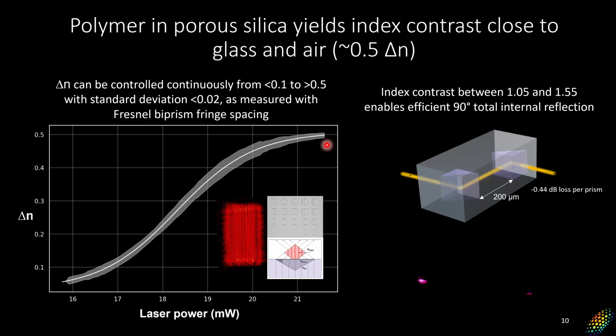And so this amount of index contrast is enough to enable efficient, basically 90-degree total internal reflection. So we've actually made these TIR prism pairs where light shines through the substrate. You shine it onto one of the prisms, it bounces between and comes out the other side versus going back through the substrate. So the sensitivity is actually very high.